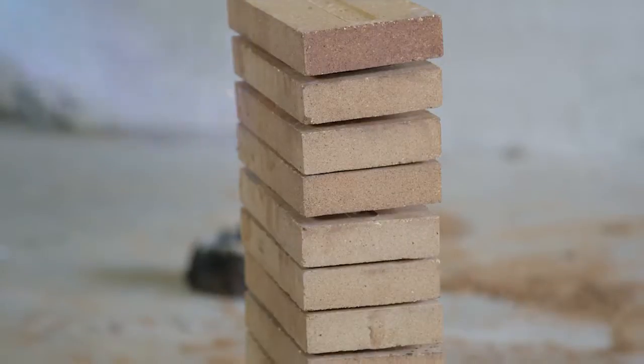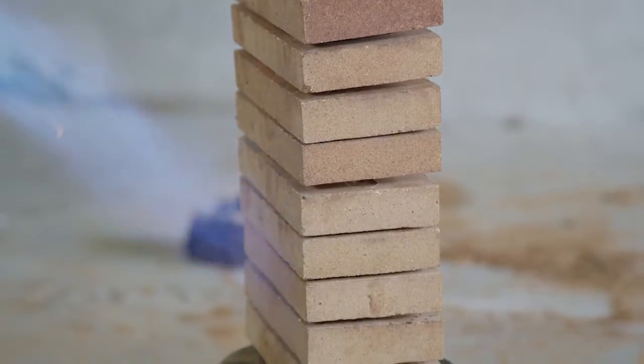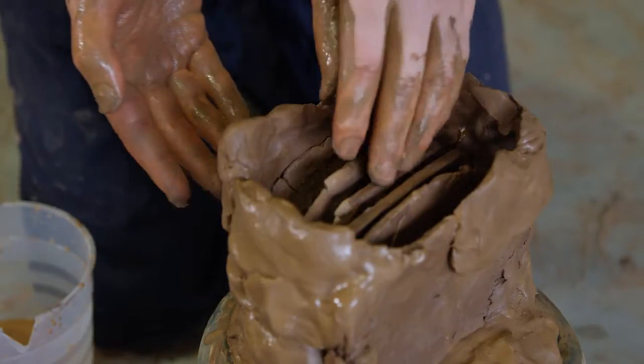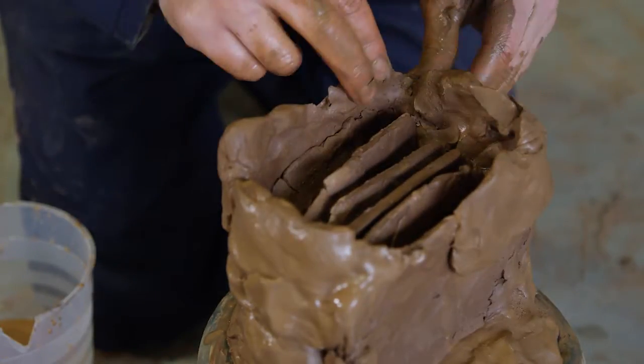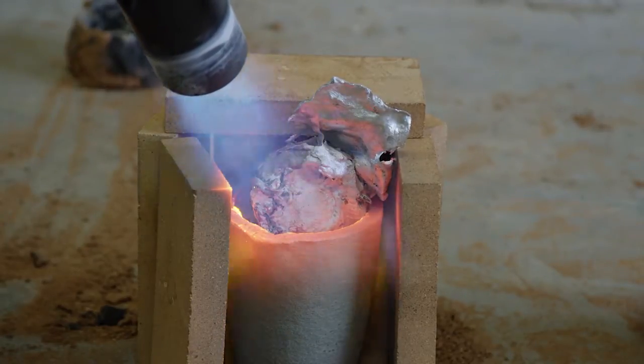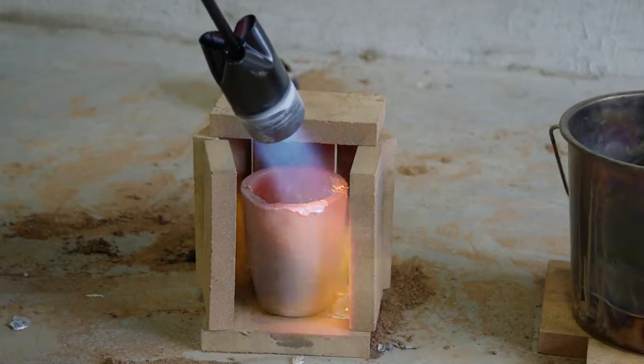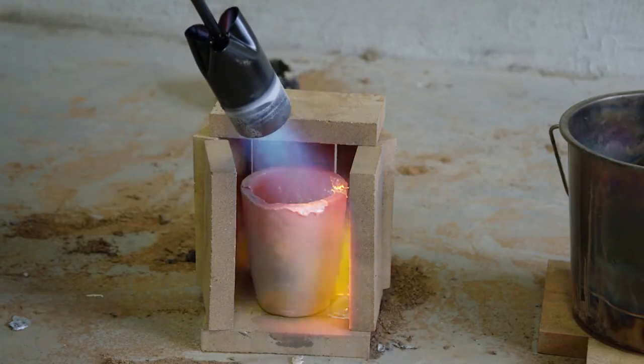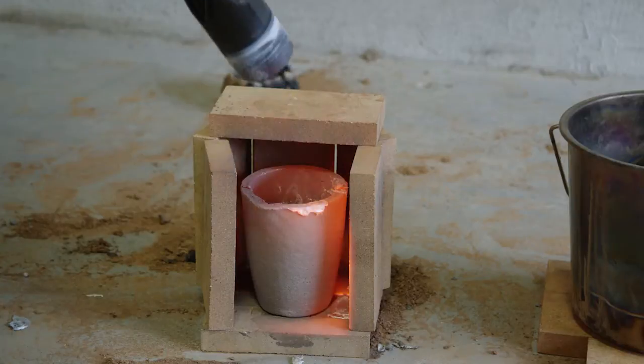We could solve this by creating a much taller riser, but by this point, the time crunch had become real, and our engineering department realized that he needed to produce something usable or I might melt him down. So he made a clay and fire brick sandwich and assembled a mold using a method that bears more resemblance to grade 1 art class than to precision crafting. To ensure on this, the final attempt, that the metal would thoroughly melt, the furnace was remade and heated until the entire crucible was red hot.